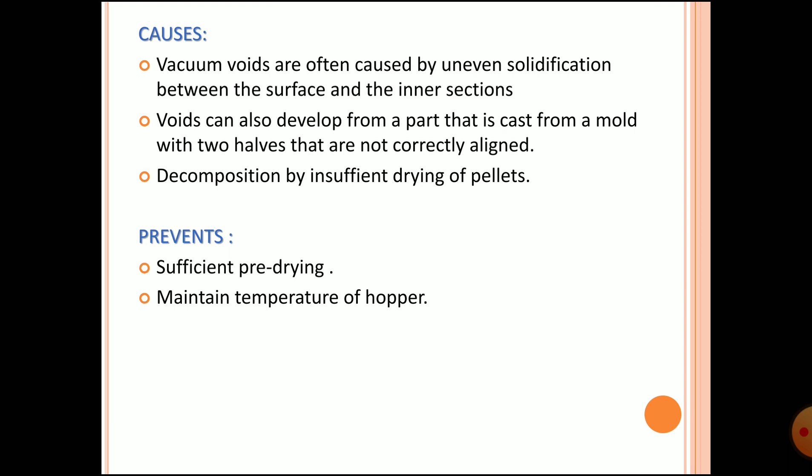For prevention: the main cause is insufficient pre-drying of the material, so you must dry the material sufficiently and maintain the temperature of the hopper. This will ensure equal solidification, and due to maintaining temperature, any air bubbles or water bubbles in your material will be removed.